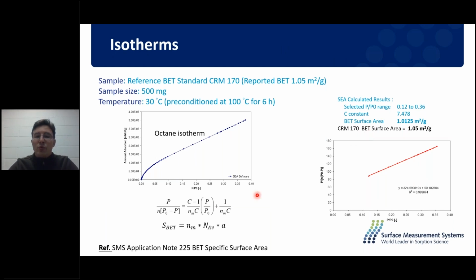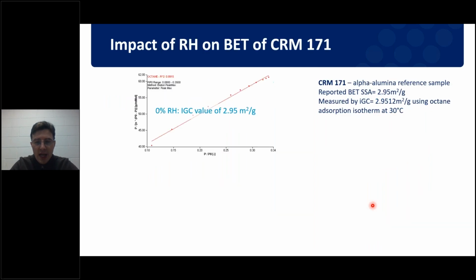Here we have a known BET standard, CRM 170, and it has a low surface area of 1.05 meters squared per gram. I preconditioned my column at 100 degrees C for 6 hours. After that, I let my column cool back down, and I ran an octane isotherm at 30 degrees C. Here you can see I was aiming for a high partial pressure to a low partial pressure, and then I find a region where I'm getting a good linear regression within the BET range. Here we can see the value I have calculated from this measurement is in very good agreement with the value we have quoted here. So this really shows that we have good performance for low surface area.